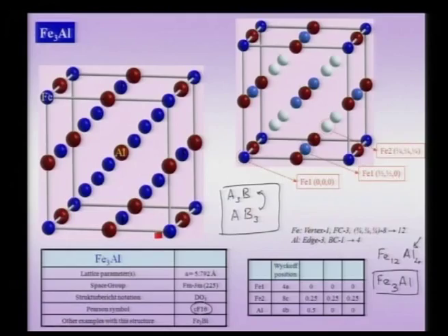Now I mentioned that I am designating two different ion positions. That means I am calling one ion 1 here, another ion 2. Now I need to understand this, and though we have not gone into the detail of what is known as the Wyckoff position, these have been designated in Wyckoff notation as 4a and 8c. We will not take up details of this, but we will understand it in our normal knowledge of coordination polyhedra later. So ion 1 is located at 0 0 0 and equivalent positions, and ion 2 is located at quarter quarter quarter positions like these and equivalent positions.